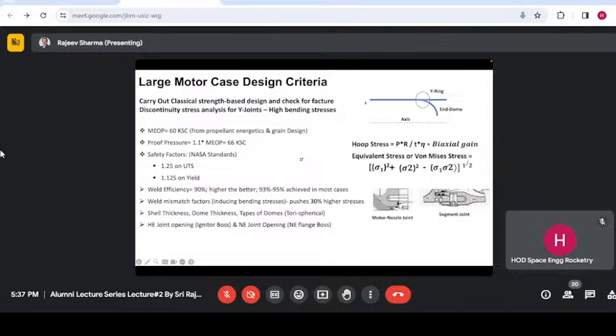When you weld a sheet or a plate to a big thick forging in the Y-ring sections, the igniter boss sections, and the nozzle and flange boss sections, you have large bending stresses because of the mismatches of the welds. Even the sheet deforms under pressure, as much as, you can calculate it for those who understand, but quite a lot. Imagine it becomes like a balloon in the centers, wherever there's the internal pressure.